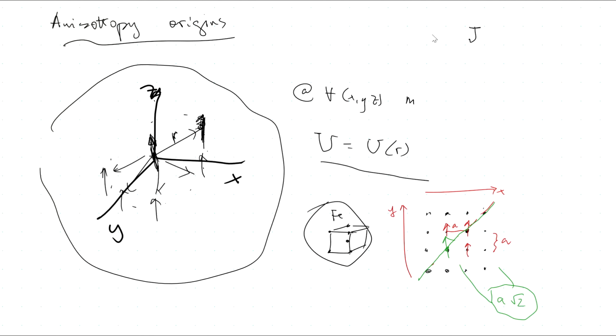At the atomic level, the exchange interaction is what defines the interaction, and J depends on what type of atoms we have, the atomic radius, but also on how far they're located in the crystal. So if you take different types of crystals, J would have a different value, and it is a characteristic value for each particular material. So then this J would be different.